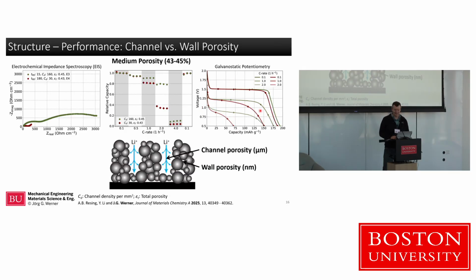Now we can also look at the raw data when you actually charge or discharge. In this case, we lithiate a battery, where we apply a constant current, and we measure the voltage. And with this lithium titanate, what you usually see is this flat plateau until at some capacity, or that's a time axis as well at constant current, it just falls off because now you put all your lithium into the material, you're done with the chemical reaction. The faster you do that, it always happens that you can put less and less lithium in it because the lithium doesn't have time to find all these particles essentially to meet them. But you can also look at this distance in plateau here versus what it should be at around 1.5 volt. That's your overpotential, which is really coming from ohmic resistances, but also from depletion effects of the lithium ions.